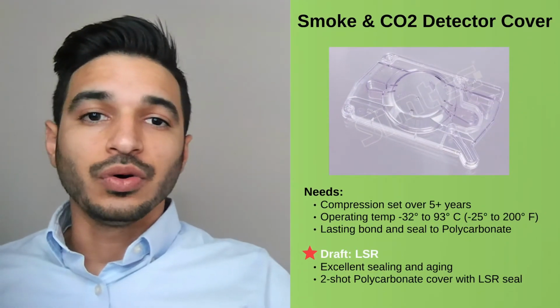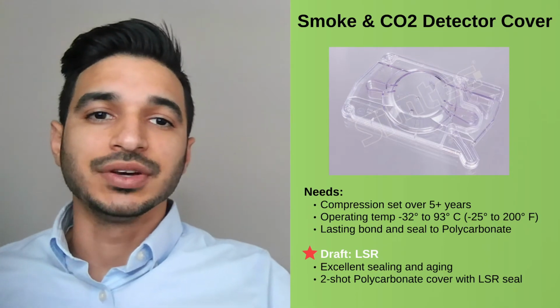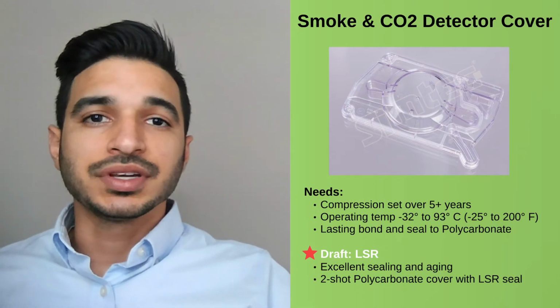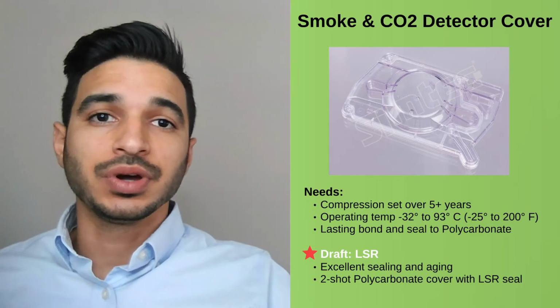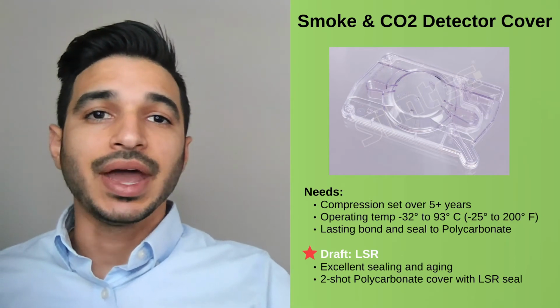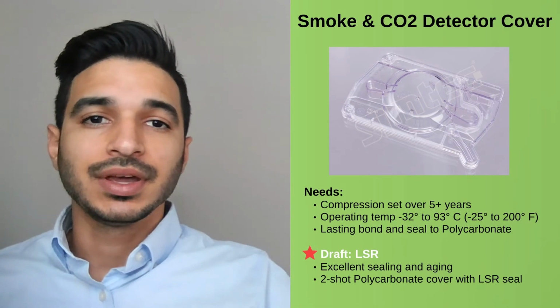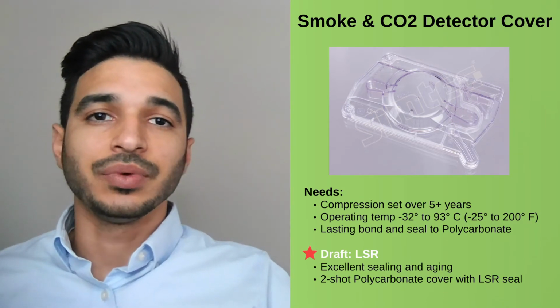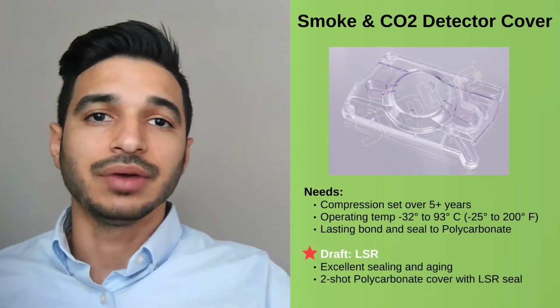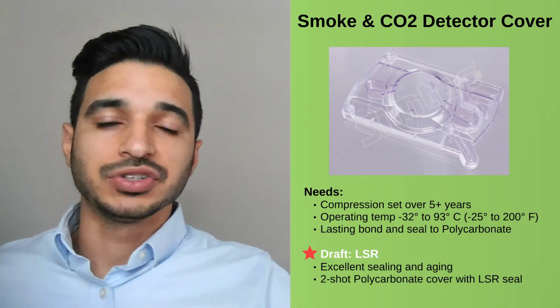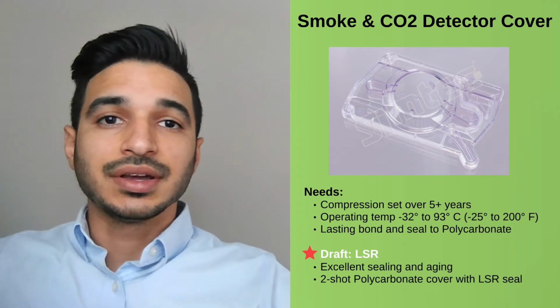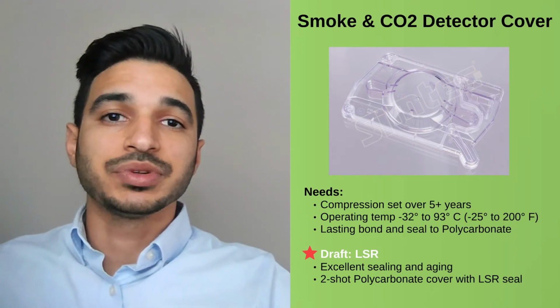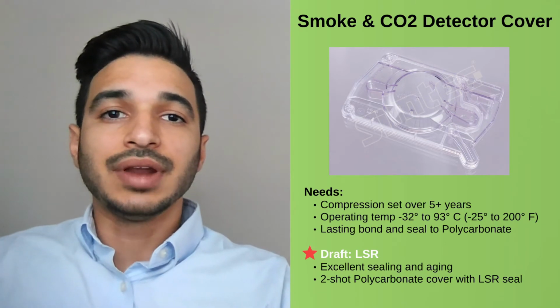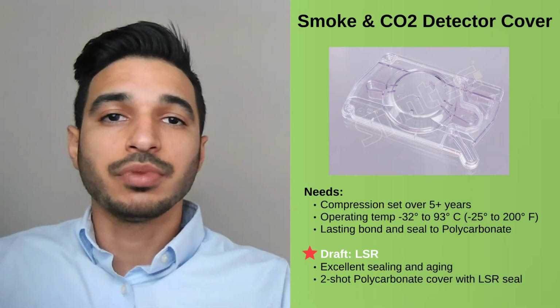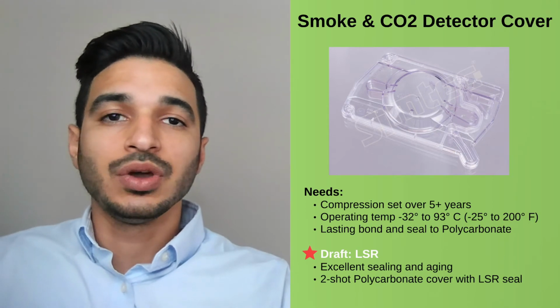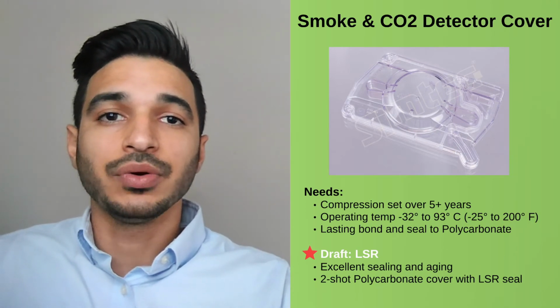So first, we want to go over an application for a smoke and CO2 detector cover. Previously, the customer was purchasing two components. One was the elastomer seal and one was the polycarbonate cover. The problem here was that when the technician would come by and remove the cover from the module, the seal would get out of the profile, and as the seal was being replaced, it would not be replaced to its original profile and cause small gaps, and therefore there was leaking where it compromised the internal components.